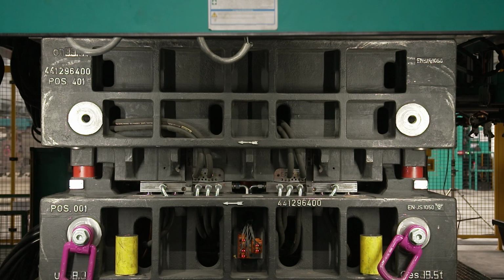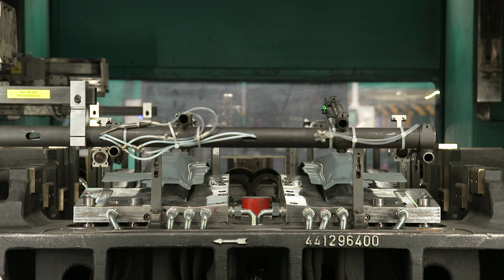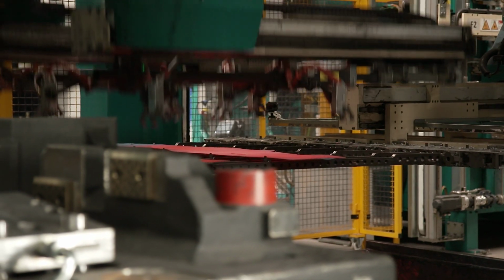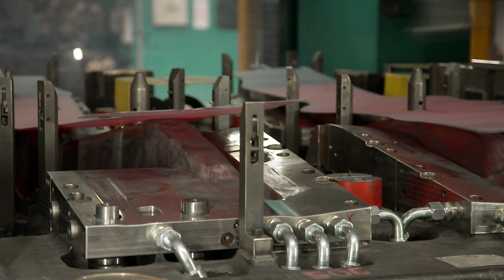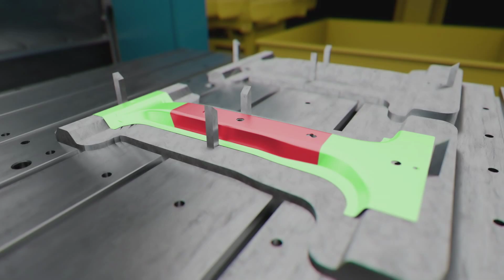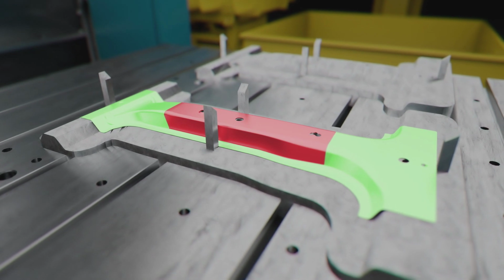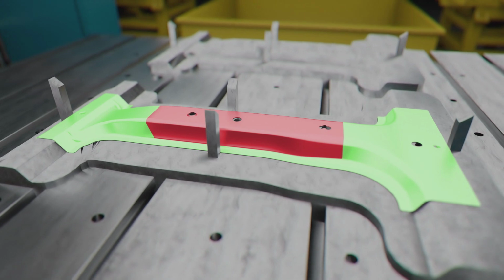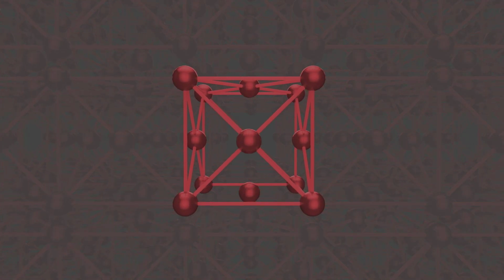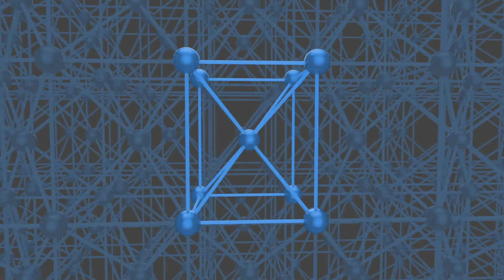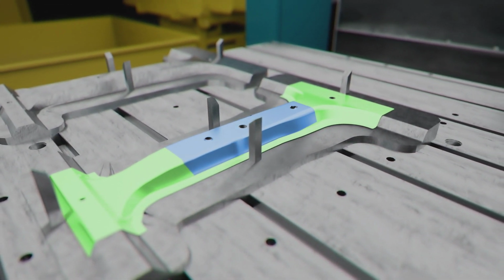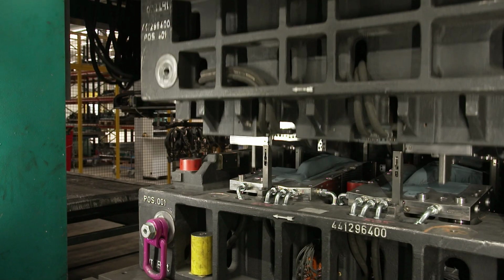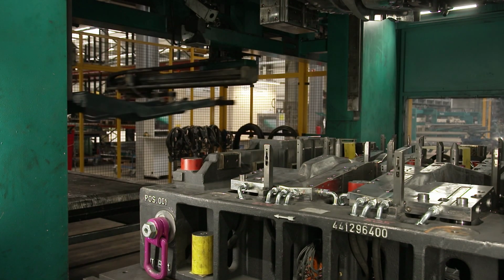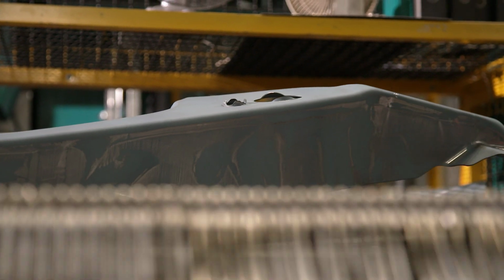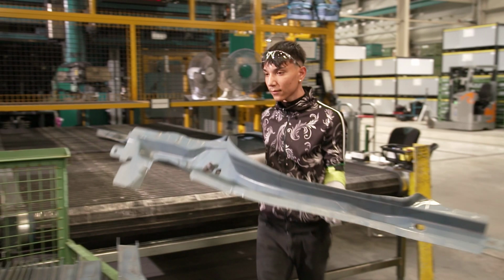The press operates at a pressure of up to 1,200 tons. During forming, water flows into the die. As a result, the hot metal is cooled to below 100 degrees Celsius in just a few seconds. In the hot zone of over 900 degrees Celsius, this rapid cooling creates another metal structure out of the austenite. The rapid cooling, called quenching, creates a slightly distorted structure, the so-called martensite. This is particularly strong. At the edges of the metal sheet, however, there is still the malleable ferrite structure. The result is a component of a vehicle body that has two physical properties and is significantly lighter than if it had been made from two different metals.